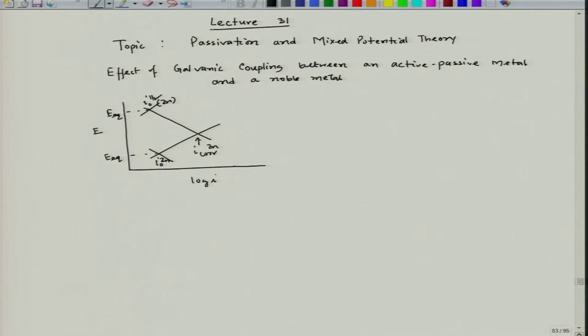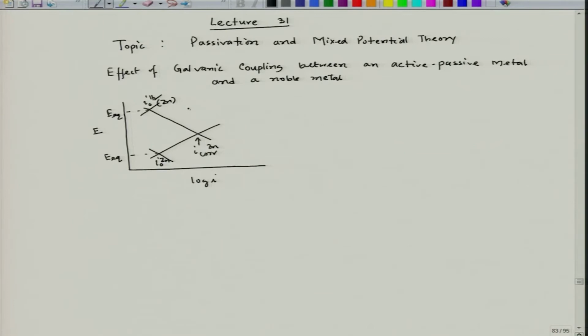Now, once we connect zinc, let us say 1 centimeter square area, with platinum of 1 centimeter square area, on platinum the hydrogen exchange current density is much higher than that on zinc surface, but E equilibrium does not change because this E equilibrium is decided by the pH of the solution, provided the atmosphere and the hydrogen gas pressure is kept at 1. Now, if the exchange current density of hydrogen evolution on platinum surface is higher than the hydrogen evolution reaction exchange current density on zinc surface, it will have its own...